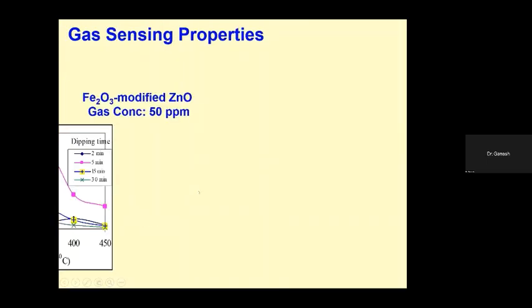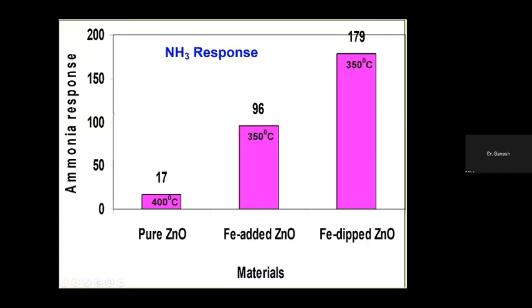Then here you see the ammonia response of pure ZnO at 400 degrees Celsius gives a response of 17. Fe-added ZnO gives a response of 96 at a lower temperature, that is 350 degrees Celsius, and Fe-dipped ZnO gives more response, 2 times the response at the same temperature. So this is the weakness of the sensor, that it operates at a very high temperature, that is 350 degrees Celsius and 400 degrees Celsius.